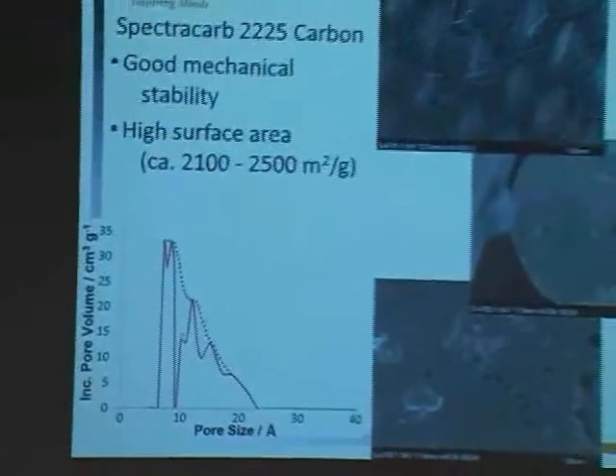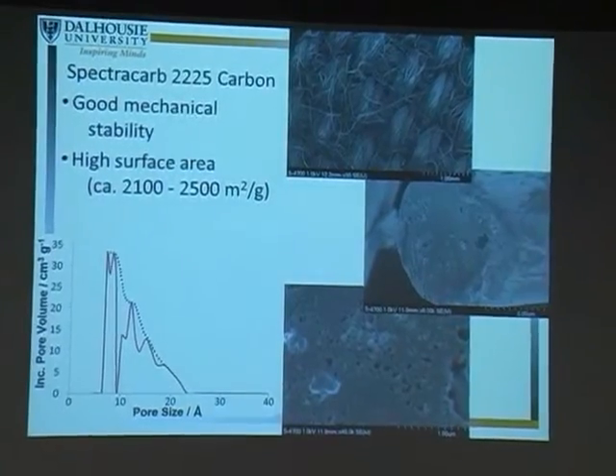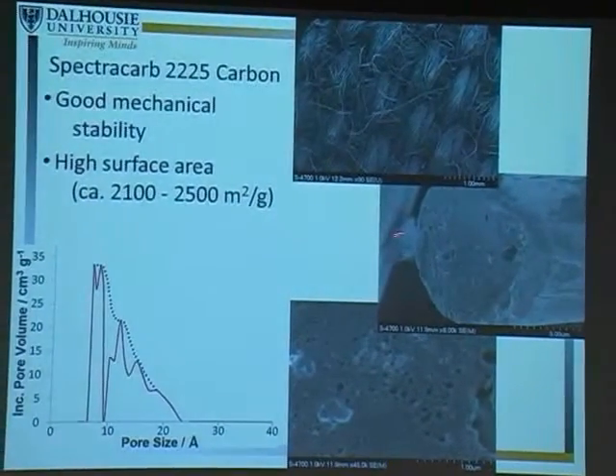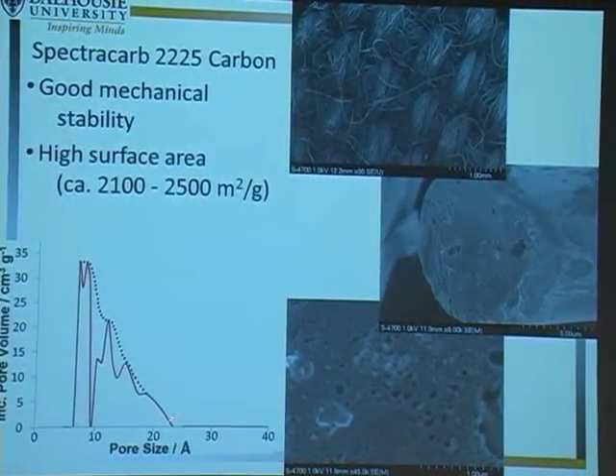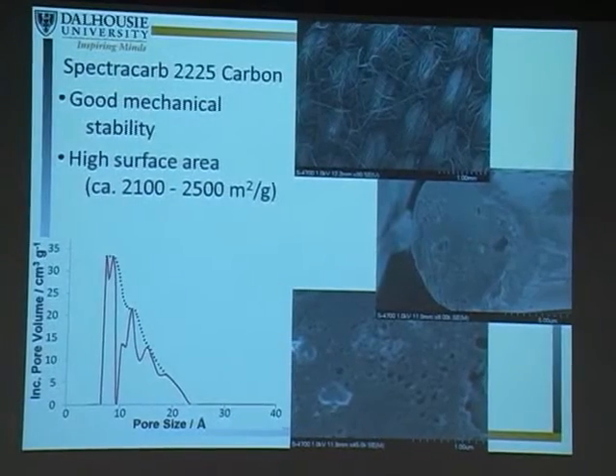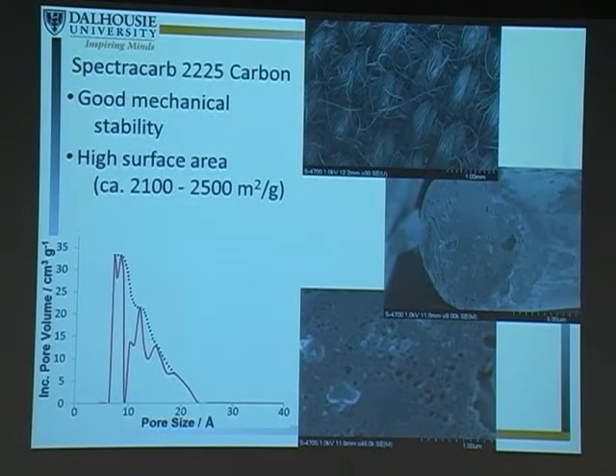So it's a carbon cloth material. You see an SEM image on the top right. One most important characteristic of this carbon material is it's a very, very high surface area, again, giving us that high capacitance. And that's because we have these fibers, they're woven together. We have pores on the fibers, and this is a result of a BET measurement. And these pores that contribute most of the volume are actually in the 10 to 20 angstrom size. So we're talking about very small pores, very high surface areas. The manufacturer BET surface area is 2,500 meters squared per gram. In our hands, when we do DFT calculations, we get about 2,100 meters squared per gram. Nevertheless, very high surface areas. So that'll give us high capacitance.